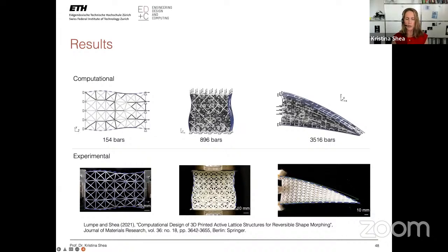And so he was able to show with a good degree of accuracy that we can create these desired morph shapes in the structures by using not the shape memory effect of the material, but rather the difference in compliance when you heat it.